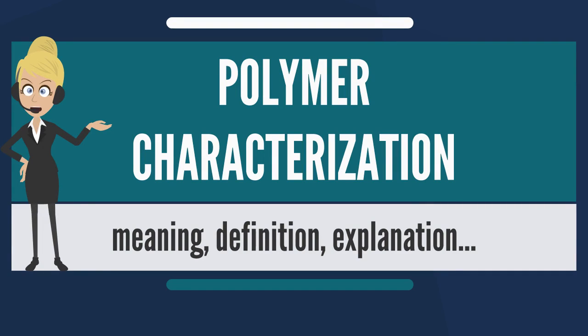Polymer morphology on a mesoscale, nanometers to micrometers, is particularly important for the mechanical properties of many materials. Transmission electron microscopy in combination with staining techniques, but also scanning electron microscopy and scanning probe microscopy, are important tools to optimize the morphology of materials like polybutadiene polystyrene polymers and many polymer blends. X-ray diffraction is generally not as powerful for this class of materials as they are either amorphous or poorly crystallized. Small-angle scattering like small-angle X-ray scattering (SAXS) can be used to measure the long periods of semicrystalline polymers.